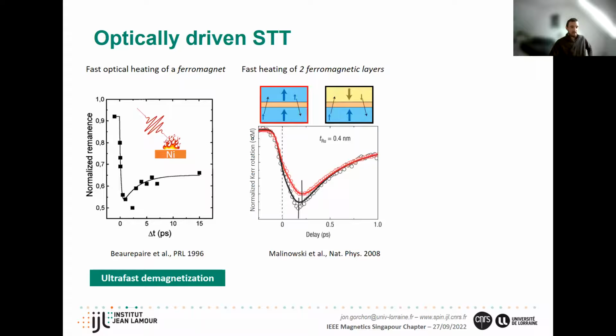And a few years later, it was discovered that if you put 2 ferromagnets separated by a conduction layer in such a way that you can get the parallel and anti-parallel configurations, and you hit this with a femtosecond laser, and you look at the demagnetization, you can see that when the layers are parallel, you get a smaller demagnetization than when they are anti-parallel. And the very simple way of understanding this is that when they are anti-parallel, you're mixing spins due to spin transport. So you get a better spin mixing, and so you get a better demagnetization.